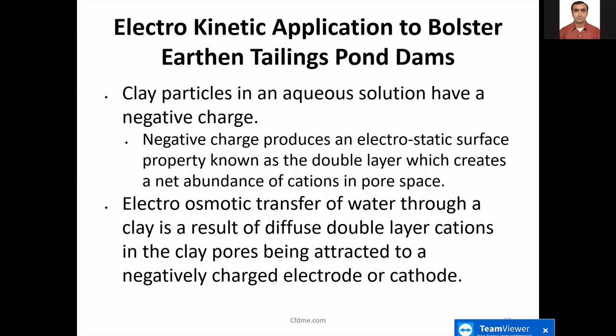Okay, clay particles in an aqueous solution have a negative charge. Negative charge produces an electrostatic surface property known as the double layer, which creates a net abundance of cations in pore space. So we believe with this, if we can neutralize the diffuse double layer, which we can do electrokinetically, that the cations could be held up within the tailings, and in that way control the seepage or the leaching, if you will, of things like heavy metals from that getting into groundwater and surface water and doing damage that way. And I think I've discussed that.